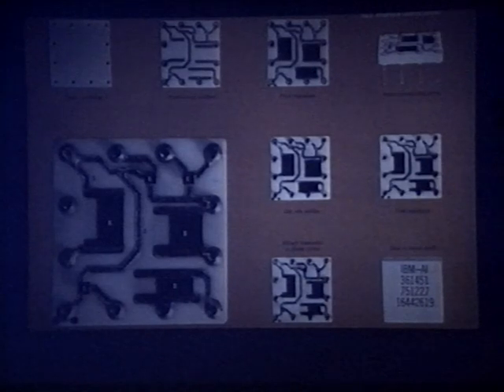Now, the thing which turned out to be quite attractive and quite unique about this is that, because before the transistors are put in place there is solder on these lands, when you put the chip on, you don't have to accurately align it. As long as you put it approximately in the right position, which is a very easy automation job, you then just put this thing into a reflow furnace, turn on the furnace, the solder melts, and the surface tension of the solder just sucks the chip into the right alignment, and you get a perfect positioning of the chip in place.